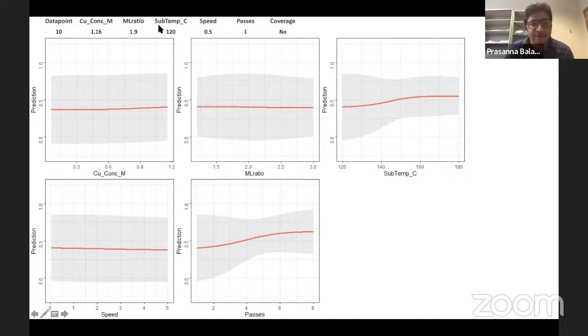And if you look at temperature as an example, this is the temperature panel here, 120 degrees, right? A prediction of probability zero indicates it will not form full coverage. A prediction of probability one indicates it forms full coverage, right? In between is the degree of uncertainty, right? So for a temperature of 120, this is where the data point would belong. This is one of the reasons why the model thought that this will not be a fully covered sample, in agreement with the experimental result, right?